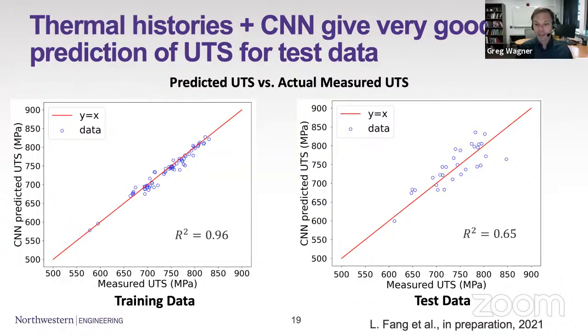We are predicting, if you're not used to looking at plots like this, it's the predicted UTS from the model against the measured UTS. You want to see everything lying on a straight line. And we come fairly close, up to what I would say is probably our experimental uncertainty, so it's hard to do too much better than that. This, by the way, is largely the work of my student, Li Xiaofeng, who is working on the publication of this data. So more details to come on exactly how we're setting up this network and testing the data.